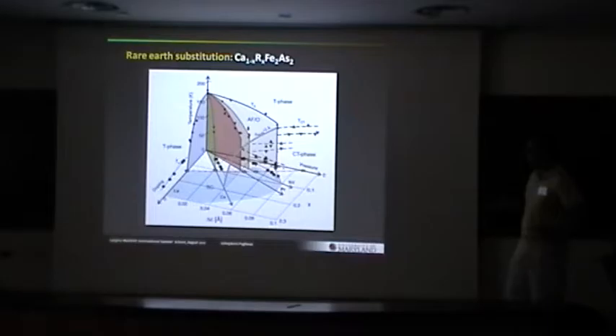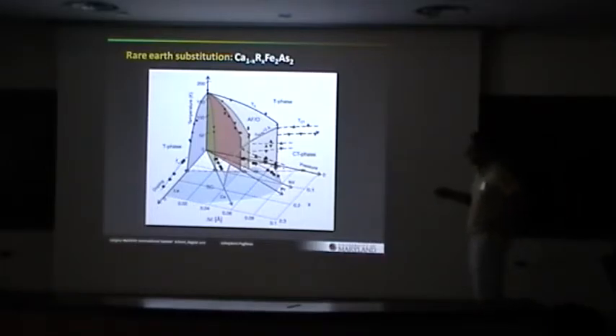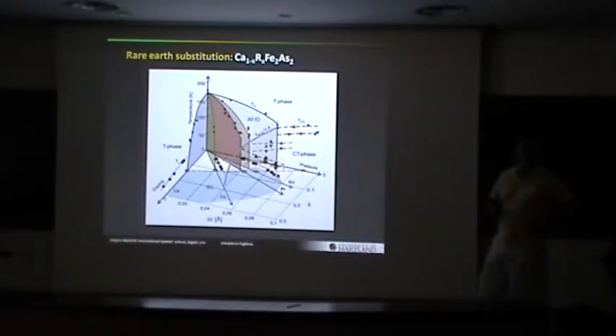here's a phase diagram. Now what we've done is, the black curve here is just showing the calcium undoped compound under pressure. So here's temperature, pressure, and here's the suppression of the magnetic order, and then it hits the collapse here. Here's the collapse transition. Now as you put in rare earth, depending on the rare earth, like I said, you induce some chemical pressure. So the other extreme is lanthanum, which does not induce any C-axis change. So I call that zero pressure. And you just suppress the magnetic order continuously, and then you have some superconductivity here. We don't see coexistence evidence.